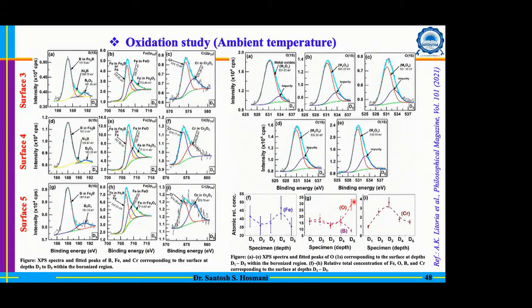Now there is another important observation, which is generally difficult to understand, but XPS gives us the information. You can see the intermediate layer, D3, has very high chromium. That high chromium is because of the accumulation of chromium in the boride phase, and that accumulation of chromium in the boride phase is associated with the lowest oxygen. What does that mean? It means that the higher the chromium content in the boride, the more superior your oxidation resistance will be.